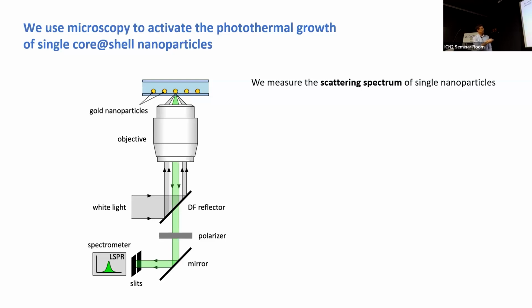So the way we did it, we put gold nanoparticles on a cover slip, and then we put it into a microscope that allows us to do dark field scattering microscopy and spectroscopy. What this means is that we have white light, which is reflected in a dark field reflector. This is a white beam of light, and it's transformed into a hollow cylinder of light. So we only send light on the outer sides of the objective, and then we focus it onto a single nanoparticle. And our objective is built in such a way that it can send light at a very high angle, but it can only collect light at a lower angle.